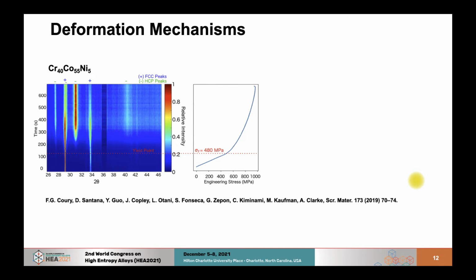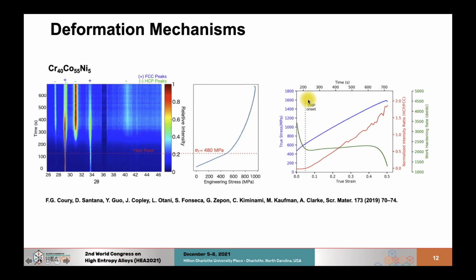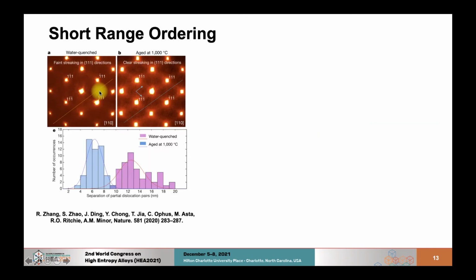And the effect we expect these deformation mechanisms have on these alloys is similar to what we see in TWIP steels, for example, or TRIP steels. Here, for example, is an in situ study on this composition, which is TRIP. And basically what we're doing is a tensile test with synchrotron X-ray diffraction. And what we're seeing is that when we have the TRIP onset, the work hardening rate stops decreasing. So this, thinking about Considere's criterion, will postpone the uniform elongation instability point to higher strengths, making the alloy more ductile. So more studies are always necessary to show particularities of this system, but this is the general explanation.